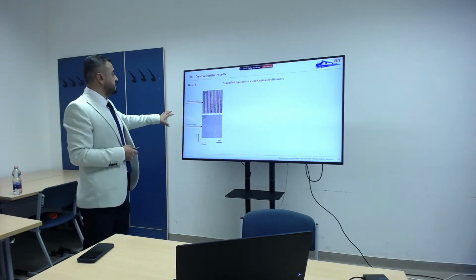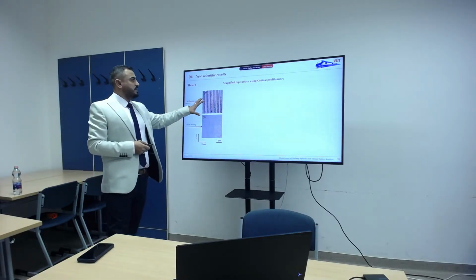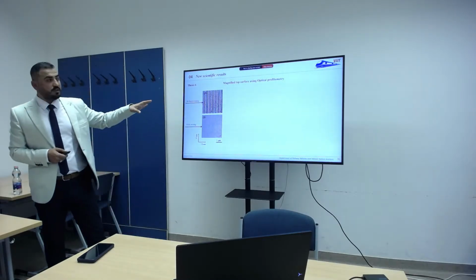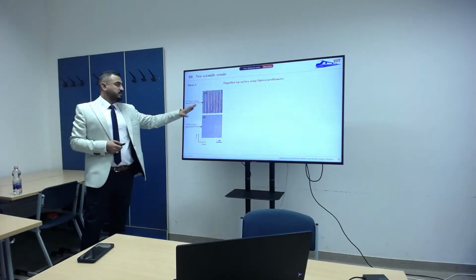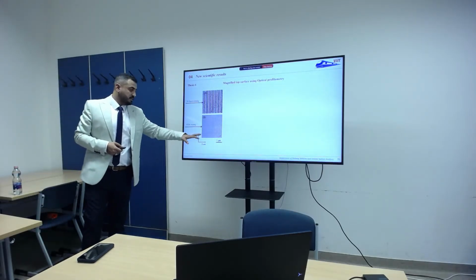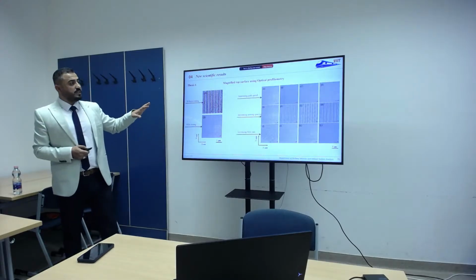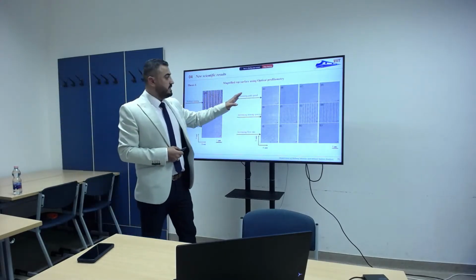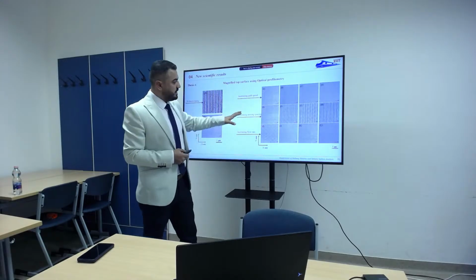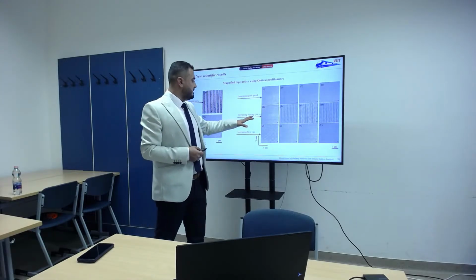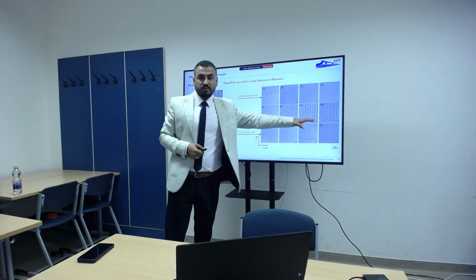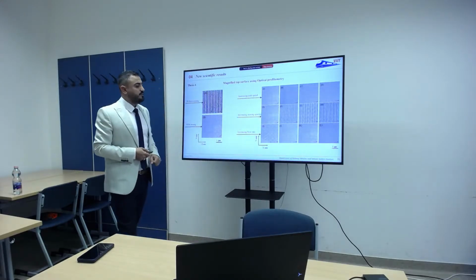And here we can see the magnified top surface from the optical profilometry. You can see the surface without ironing, and this is after the ironing. And here you can see how each parameter was investigated independently. And we can see obviously that increasing the ironing spacing was the most important factor in minimizing the surface roughness.